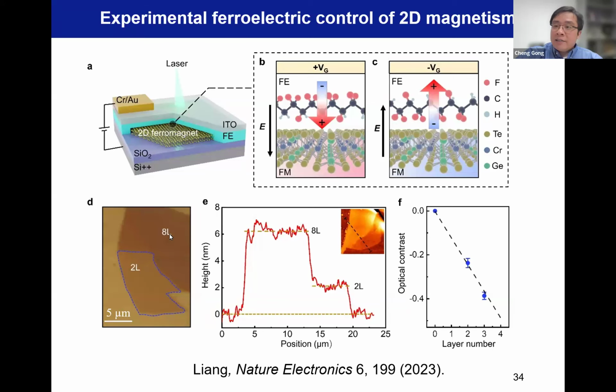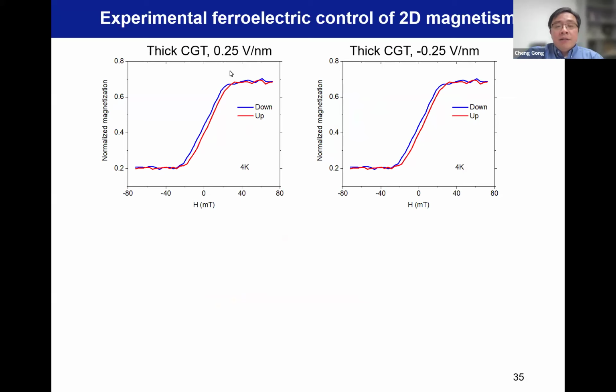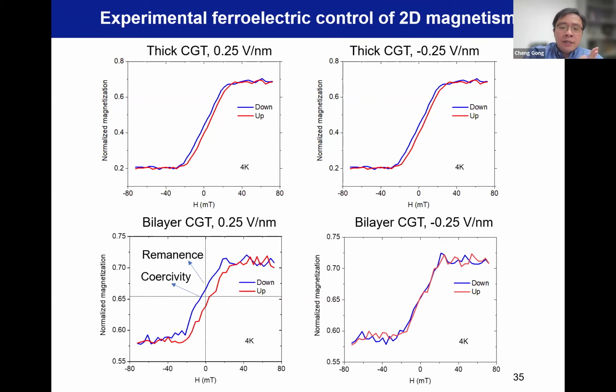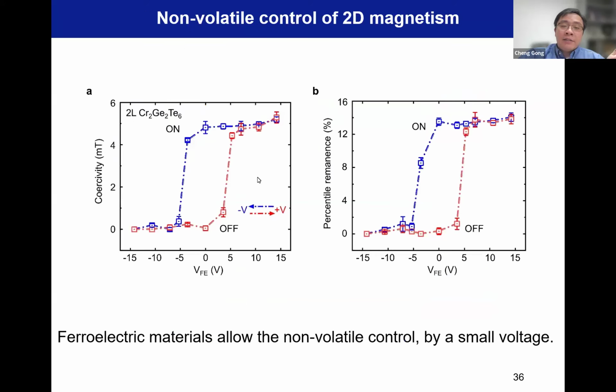So for the two layer and eight layer samples, we'll do a comparison. For the eight layer sample, when we apply positive field, negative field, you almost see nothing changed. And for the thinner sample, the two layer sample, you can see a hysteresis loop opened and closed. If you keep track of the different voltages we apply, corresponding to different electric fields, voltage-dependent remanence or voltage-dependent coercivity, you actually can get this curve. So it's a hysteretic dependence, a non-volatile effect. This is certainly a hallmark feature of ferroelectrics. It's not a pure electric field control or electrostatic doping control, which is volatile. Here it's non-volatile and allows you to only use 5 volts.